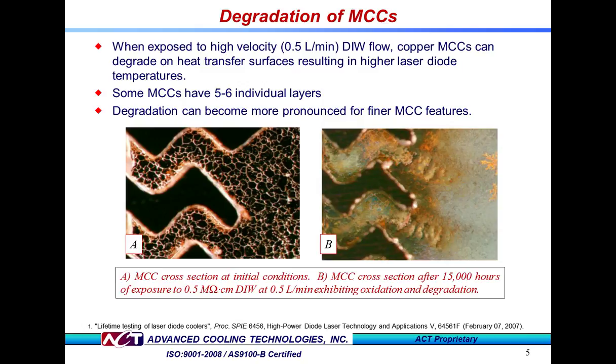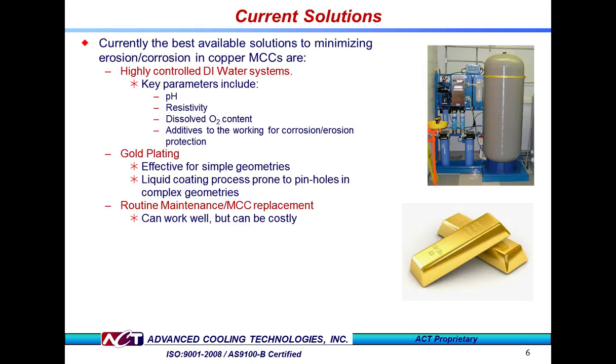The picture on the left is a cross-section of a virgin copper microchannel cooler. The picture on the right is that same cross-section after being exposed to 15,000 hours of a 0.5 megaohm cm DI water system at a flow rate of 0.5 liters per minute. The degradation that can be seen on the right is quite obvious.